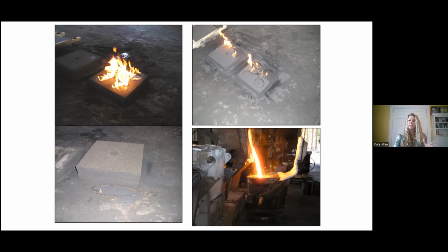The iron comes out of the furnace anywhere between about 2,100 degrees to 2,500 degrees. And different molds are poured at different temperatures. So like the thinner the casting, the lower the temperature. But it's really important that you have controlled cooling to prevent the casting from cracking. So you have to bring that temperature down slowly.